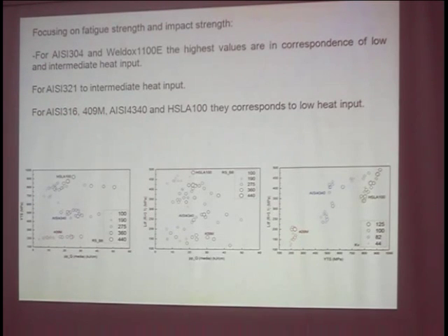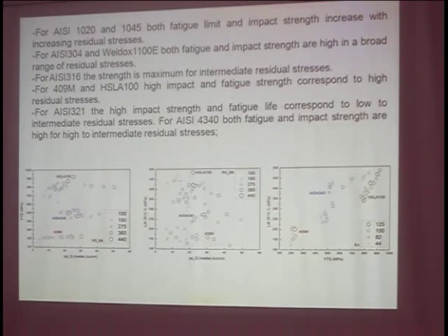And for AISI 316, 409M, AISI4340 and high strength low alloys, the optimum corresponds to low heat input. So you find very different situations. For each kind of steel, you have very broad processing conditions to be employed, and very different processing conditions to be employed for optimizing the mechanical properties. For example, for AISI 1020 and 1045, both fatigue limit and impact strength increase with increasing residual stresses.